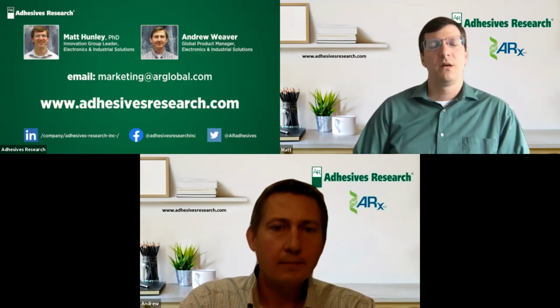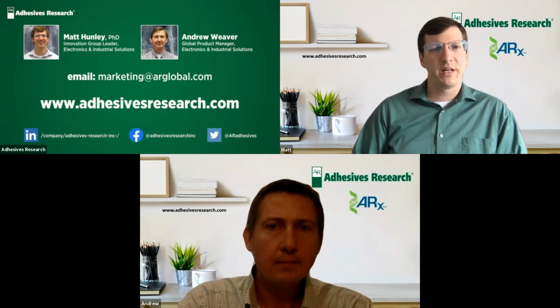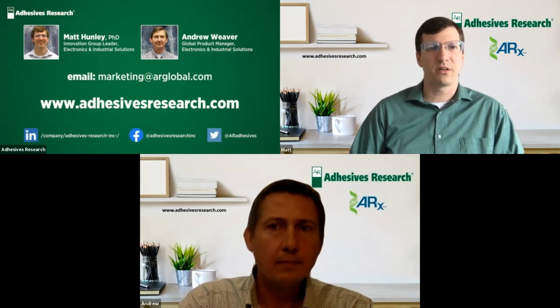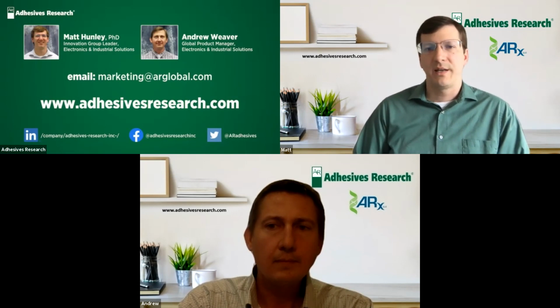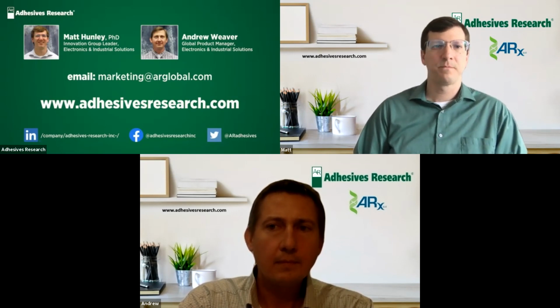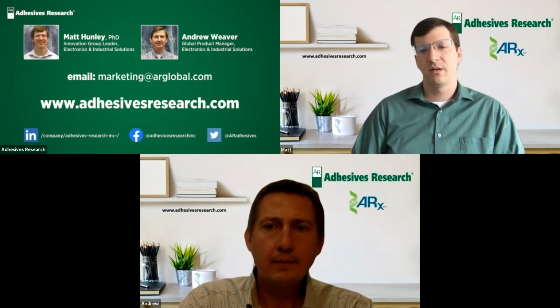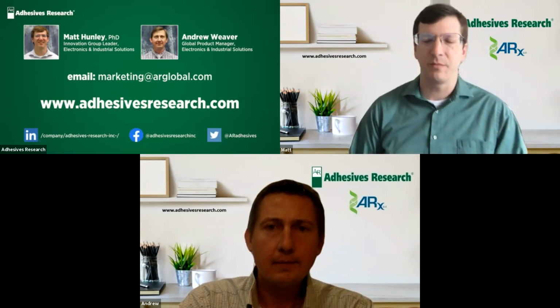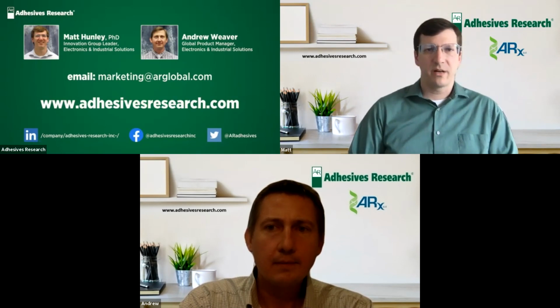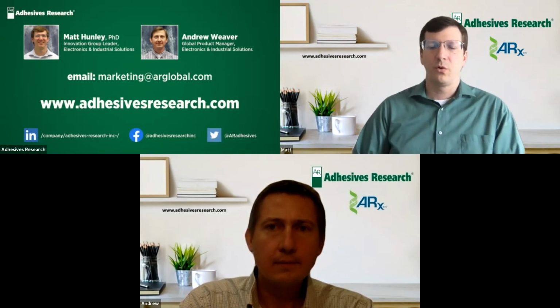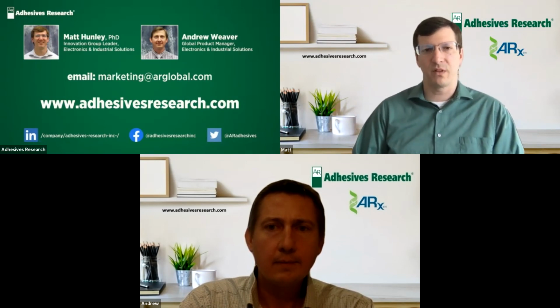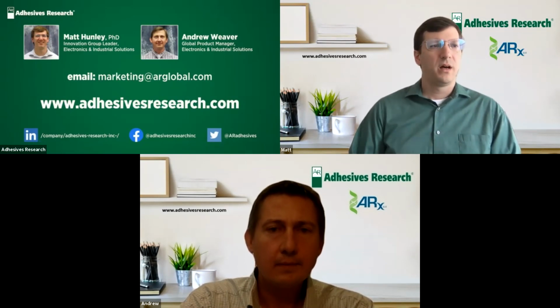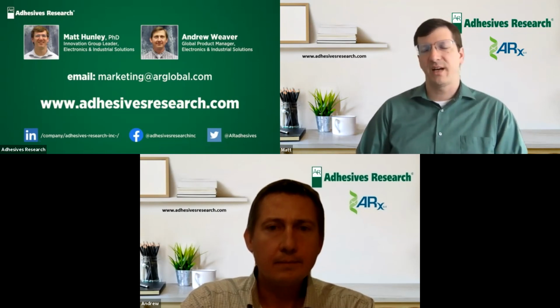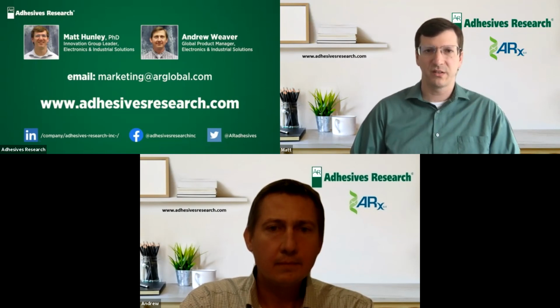All right. On the next question, can the barrier adhesives withstand thermal cycling and environmental exposure? Yes, it's very similar to what we talked about earlier for the heat seal versus PSA conductive adhesives. So we have barrier adhesives with different chemistries. Some chemistries are much better at higher temperatures than others. So we have some that are better at lower temperatures where we don't have a problem with flow under temperature or under heat. And we have some other barrier adhesives that can withstand higher temperatures, closer to 85 degrees Celsius.